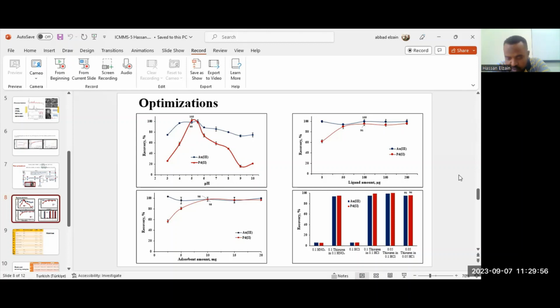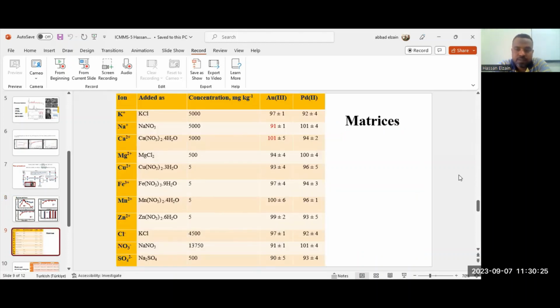For eluent type, we tested 6 different types of eluent. We have quantitative results with 4 eluent types. We selected the last one, 0.05 molar thiourea in 0.05 molar HCl. This is the matrix effects. We have tested these ions at this concentration. Our results were quantitative and ranged from 91% to 101% as recovery values.